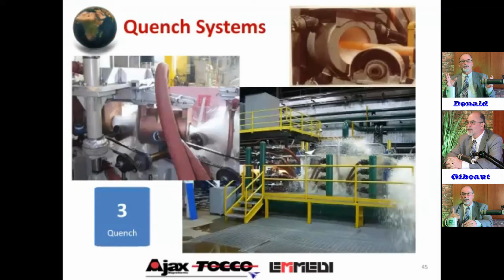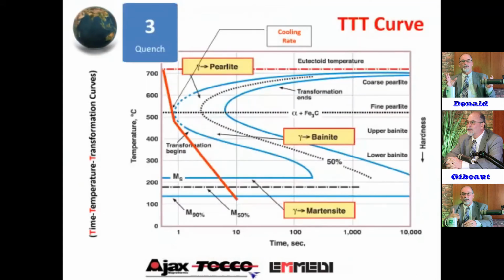Here's the quench barrel. The upper right, the lower bottom shows that aggressive quench, throwing quench everywhere. But we have containment systems that control that, but you see a grating in the floor. Now here's the TTT curve. This is where our quench was designed to. And the bottom line is you have to quench that thing out below this MS point to get a uniform grain structure, martensitic grain structure. And as you can see here, the time to do this job is roughly 10 seconds. So you're really working hard in those first couple, especially in that first barrel where most of the work is done, and we have a second.